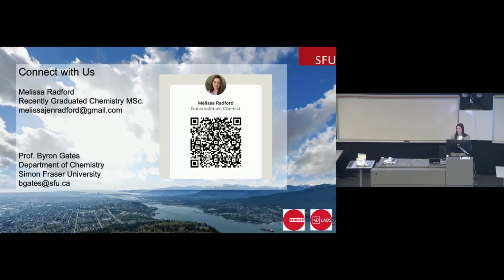Yeah, so we were taking a look at that through dynamic light scattering measurements, because that was one approach that we thought could happen, but it doesn't seem that that is majorly happening. The distance in between the particles is pretty well dispersed, and they disperse well in the solution that we have them in. We have them in isopropyl alcohol, and they disperse pretty readily in that. And they are stable for a couple of days before they start crashing out, but likely due to their size, we haven't been able to confirm whether or not they're having some dimerization yet. It is a little challenging once the functional group has been added to figure that out.